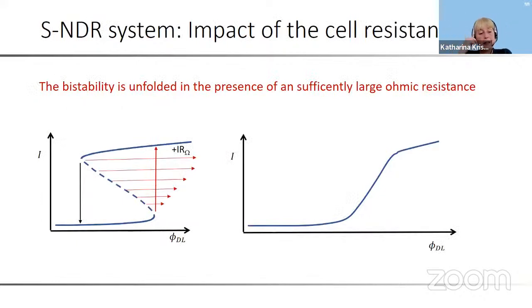Okay, what happens if we have an S-NDR system, a chemical bistability, and we happen to have some IR drop in the electrolyte we cannot compensate? Well, then actually we have a small correction at this lower part of the negative differential branch, and a large correction where we have a large current. And in this case, we don't form the bistable region, but we unfold it. We get a curve which becomes monostable.